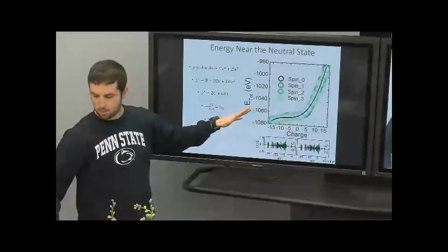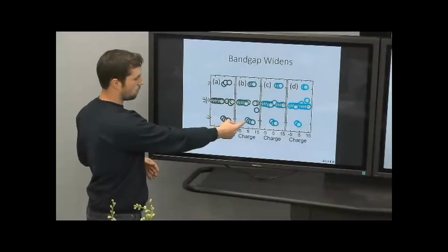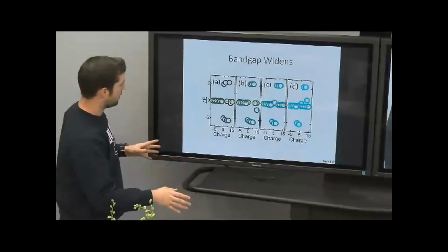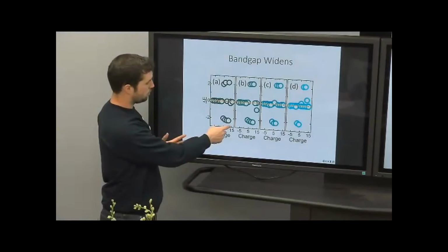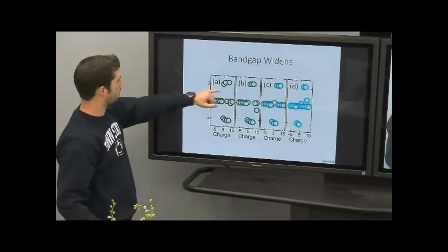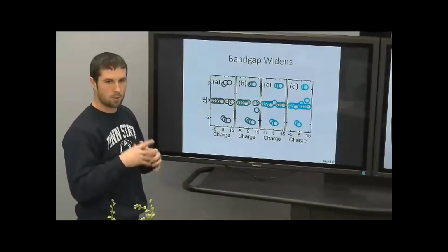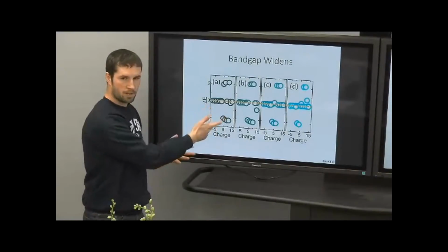Looking at these models, we then explored the band gap for these ones, which is here. I didn't mention we looked at different spins of 0, 1, 2, and 3. So this is spin 0, 1, 2, and 3, and we looked at the band gap for all these different oxidation states. For high oxidation states from about 3 to 10, we can see that the band gap considerably widens to about 2 eV. Since we did this for both alpha and beta electrons, we multiplied the band gap of the beta electrons by -1, so that's why we have a negative band gap here.